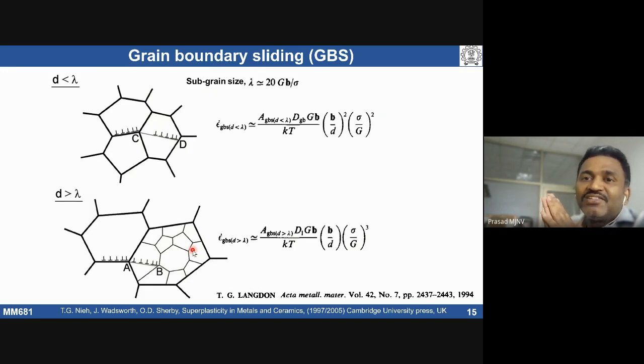That's where, if we talk about directionally solidified material, we have DS grains, elongated coarse grains, compared to polycrystalline material. The grain boundary sliding activity is going to be controlled in a DS grade as compared to polycrystalline material, because most of the boundaries have a low angle boundary character. Grain boundary sliding also depends on the misorientation angle of the boundaries. The higher the misorientation angle, the easier the grain boundary sliding. Any more doubts?